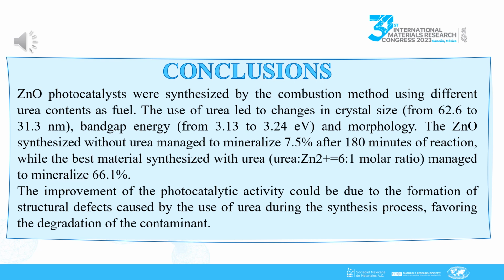The zinc oxide synthesized without urea managed to mineralize 7.5% after 180 minutes of reaction. The best material synthesized with urea, zinc oxide urea 6, with a 6 to 1 molar ratio, managed to mineralize 66.1%.